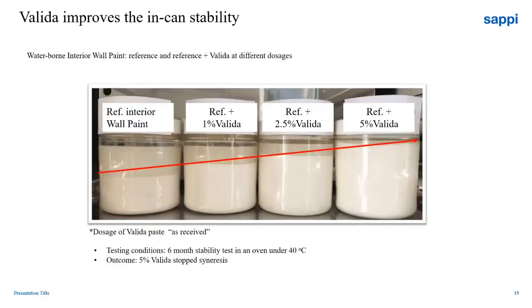First benefits, I would like to show you the improvement in lowering the syneresis issue or challenge. Valida is highly effective, in fact, in lowering the syneresis, as you can see here. The reference formulation shows a high degree of separation. Already introducing 1% of Valida into the formulation, the degree of syneresis basically is halved, until almost solved when adding 5% of Valida into the formulation. And I would like also to point out that this formulation successfully passed a 6-month stability test in an oven under 40 degrees.